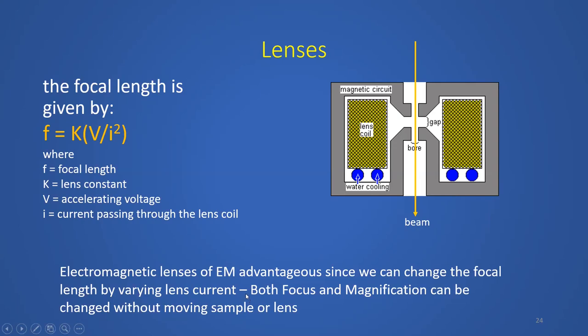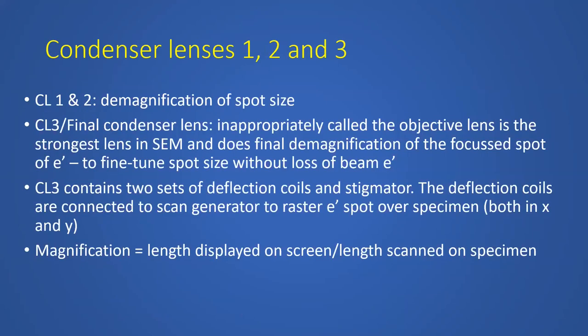Unlike in a light microscope, where for magnification you have different objective lenses in the nose piece, typically 5x, 10x, 40x, 60x, 100x, so you need to switch between the objective lenses. And then to focus, you need to work on the working distance, so you need to bring it closer. As you increase the objective lens power, for a 100x objective you need to work very close to the lens, and for a 5x it would be further away. But in an electron microscope, the advantage is that simply by changing the lens current, you can focus and magnify without physically moving the sample or the lens. This is very useful. You don't have to change the lenses or move your sample to focus and magnify.